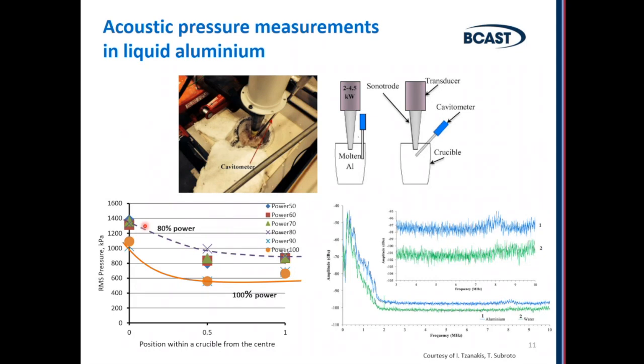And that's because you have not only attenuation of acoustic waves in the liquid, but also shielding of acoustic waves from the melt or from the liquid by the cavitation zone. You can imagine that the cavitation zone is a zone where you have a lot of bubbles. So you have not a continuum liquid medium anymore, you have a bubbly liquid. And bubbly liquid attenuates very quickly, or let's say absorbs very quickly, acoustic energy in itself. Which means that if you have a very well developed cavitation zone, there are a lot of things happening inside, but not much going outside this cavitation zone. All energy is consumed within.